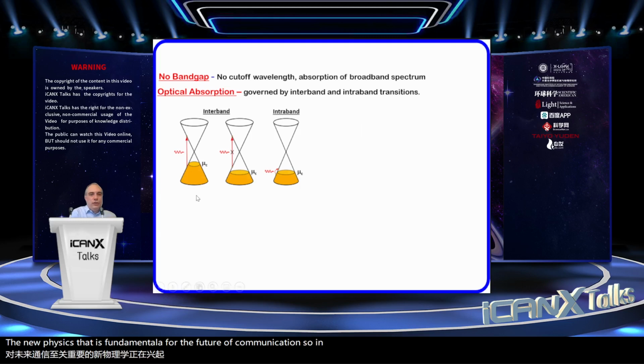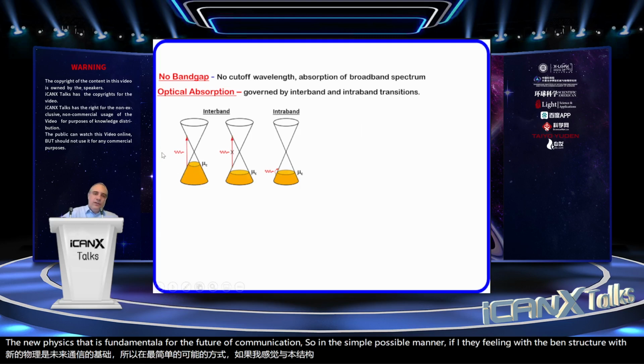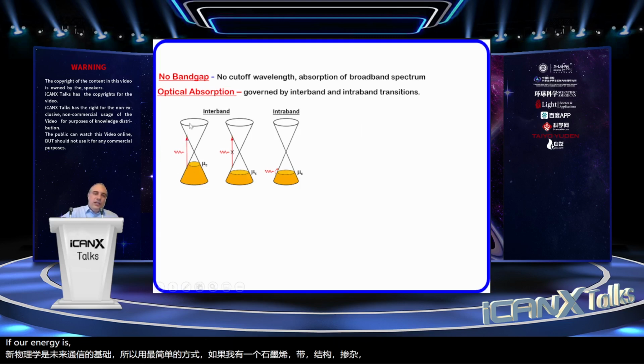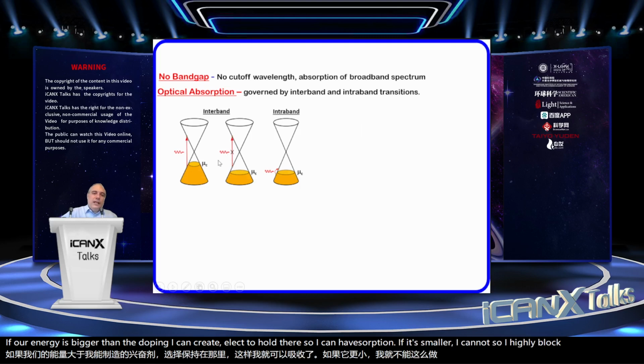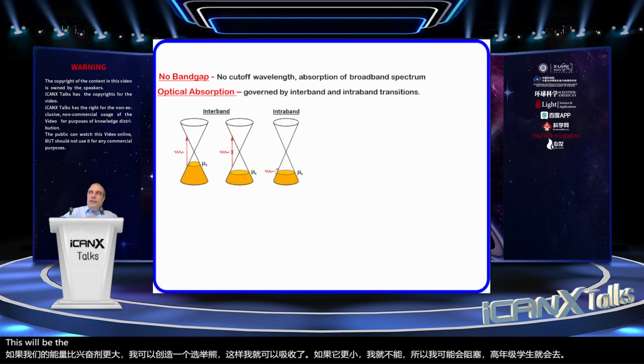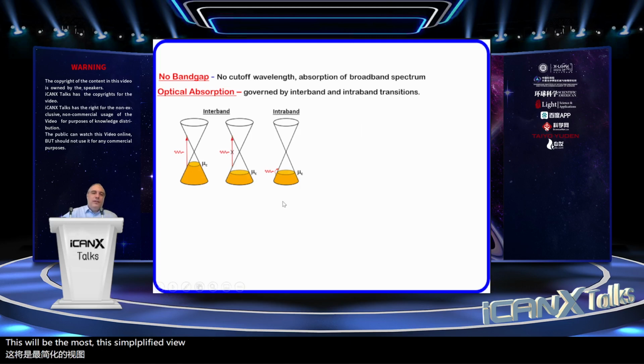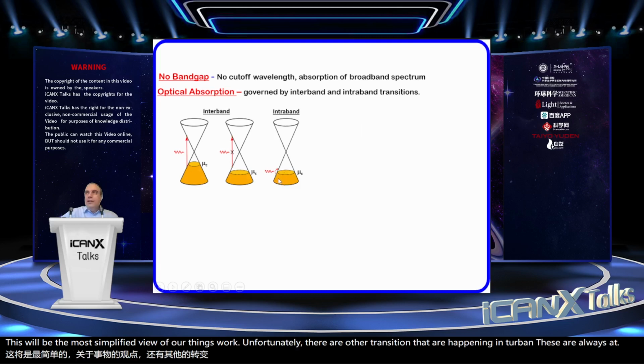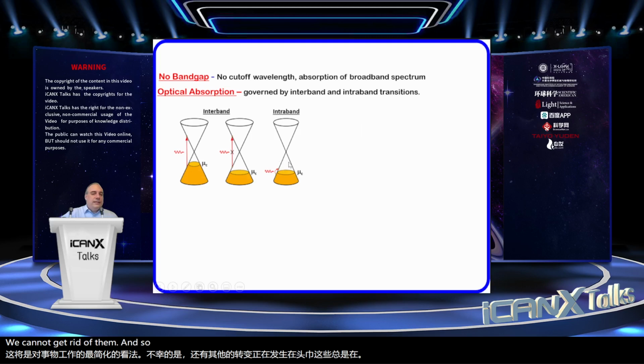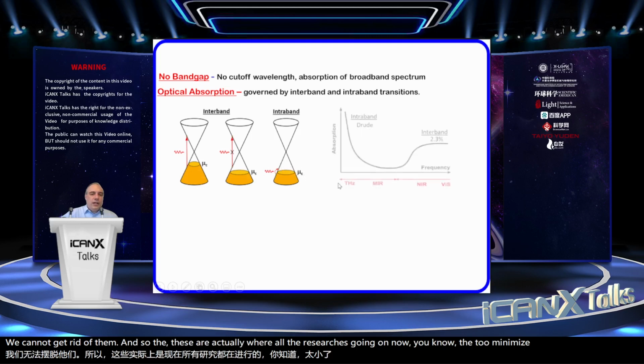So in the simplest possible manner, if I have a graphene with a band structure with a certain doping, if our energy is bigger than the doping, I can create an electron hole pair, so I can have absorption. If it's smaller, I cannot, so I have Pauli blocking and the signal goes through. This will be the simplified view of how things work. Unfortunately, there are other transitions that are happening intraband. These are always happening. We cannot get rid of them. And so these are actually where all the research is going on now in order to minimize this absorption.